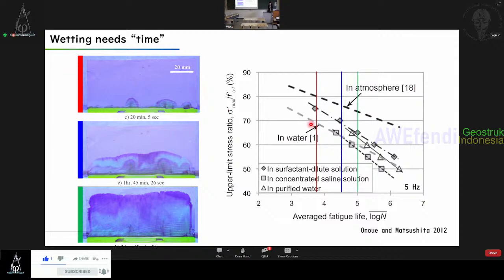But when we think about how water penetrated, for example, the x-axis is fatigue life. Fatigue life means time. And the vertical axis is how strong the material is due to fatigue. For example, this red point is only 20 minutes, blue is approximately 1.5 hours, and green is approximately 3 or 4 hours.